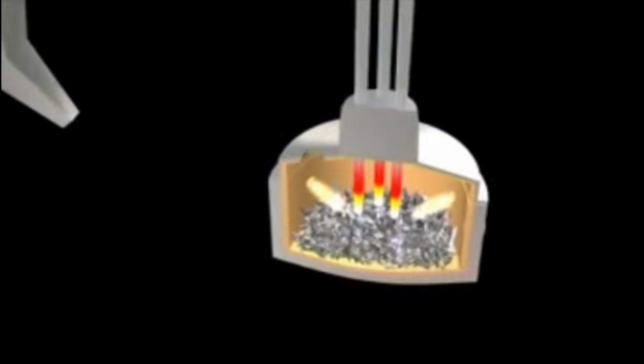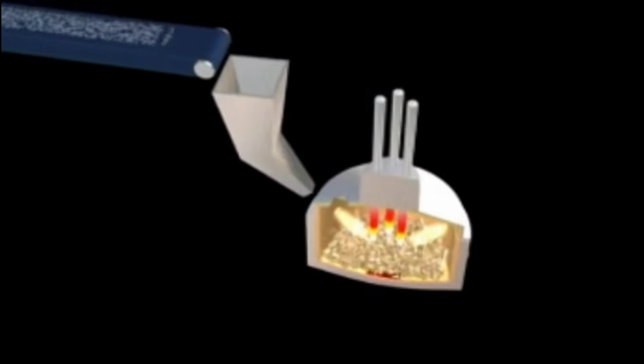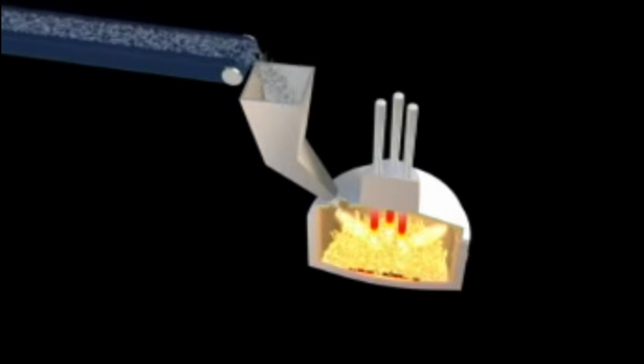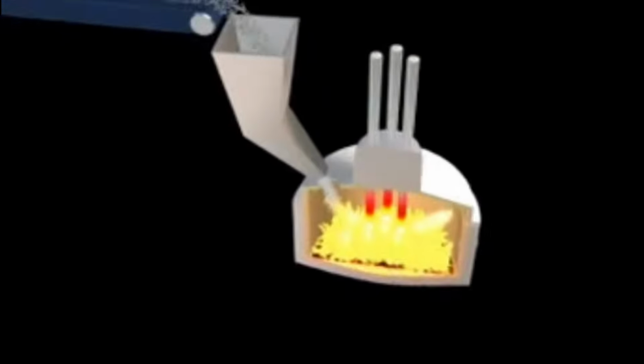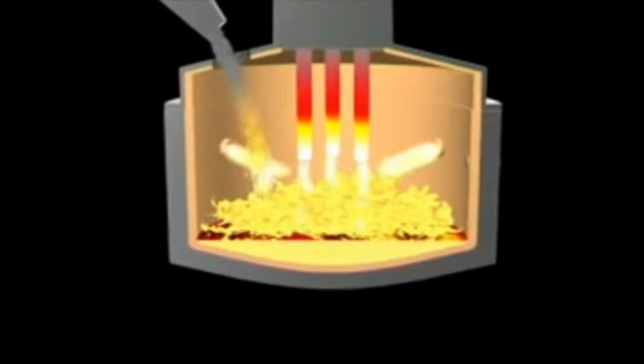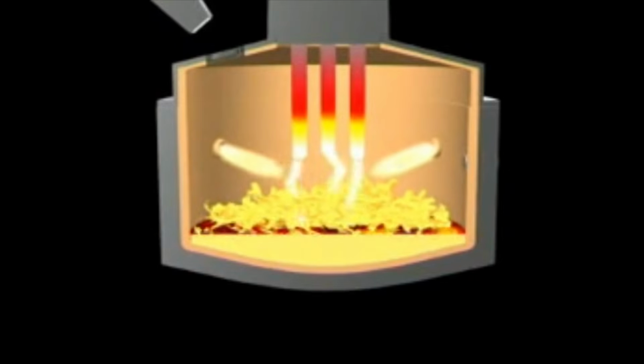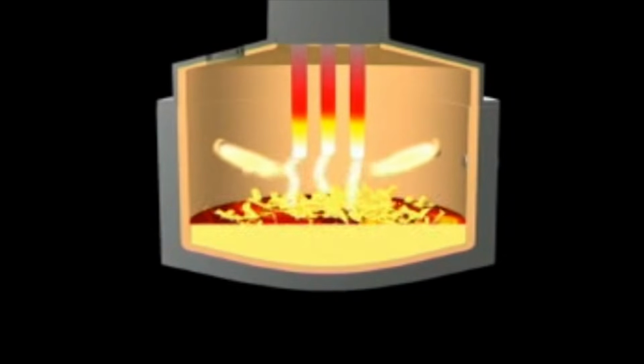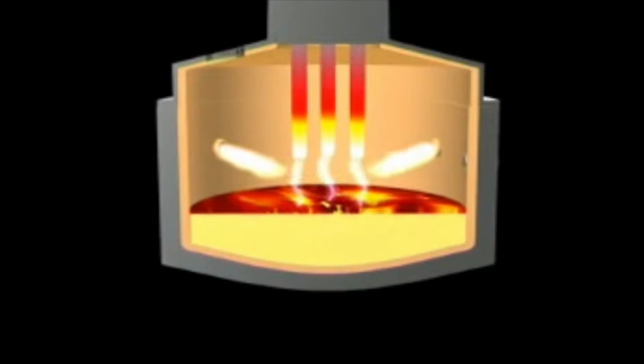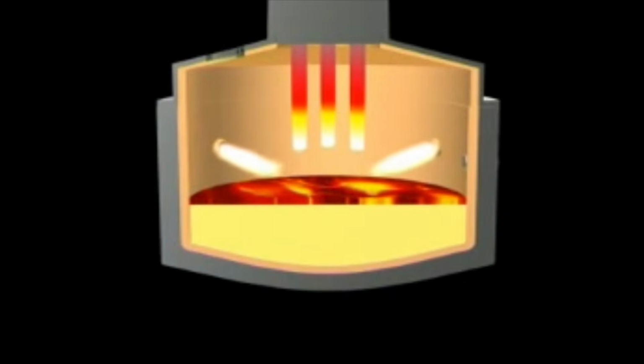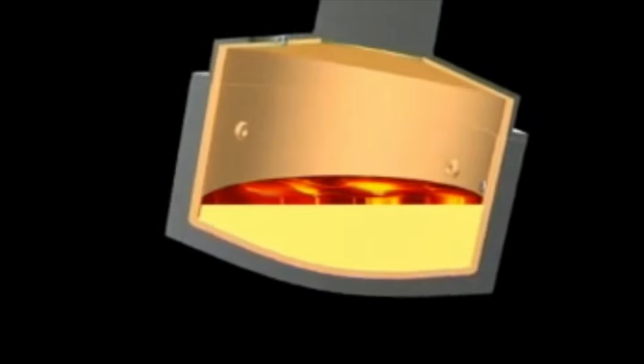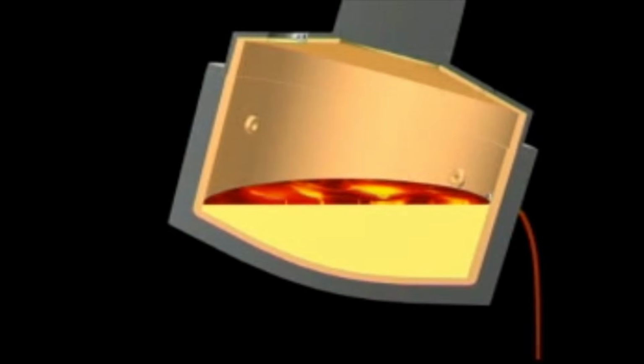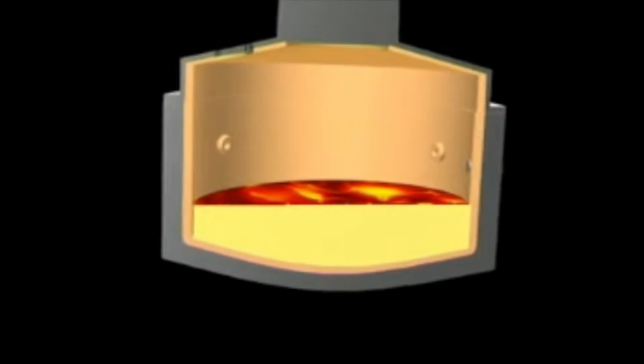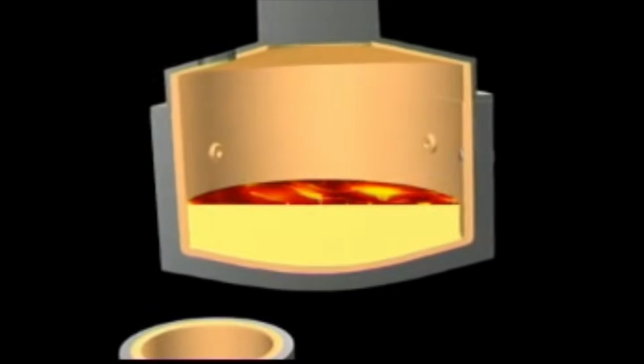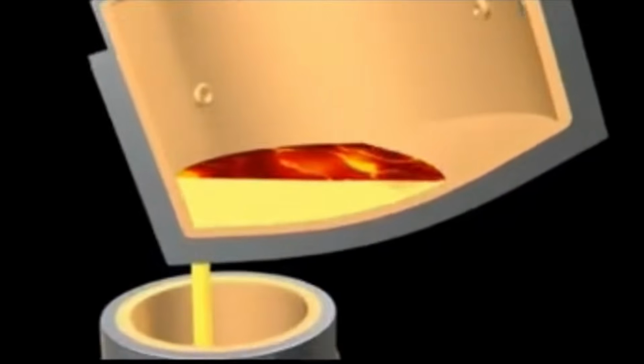In the second stage, the charge is completed by continuously feeding direct reduced iron, sponge iron. During this phase, the bath reaches operating temperatures of approximately 1,650 degrees Celsius. The process requires an electrical power input of around 90 MVA to maintain stable melting and refining conditions. After slag removal, about 80 tons of molten steel are tapped into a ladle and transported to the refining station.